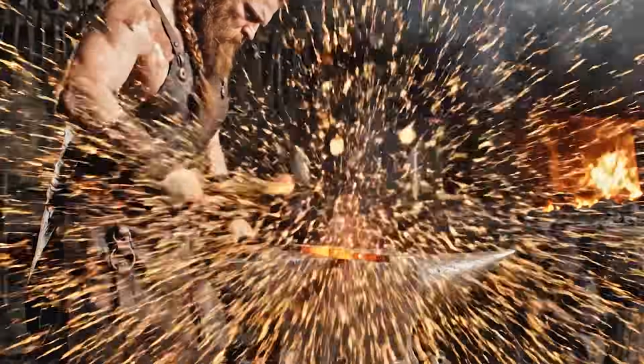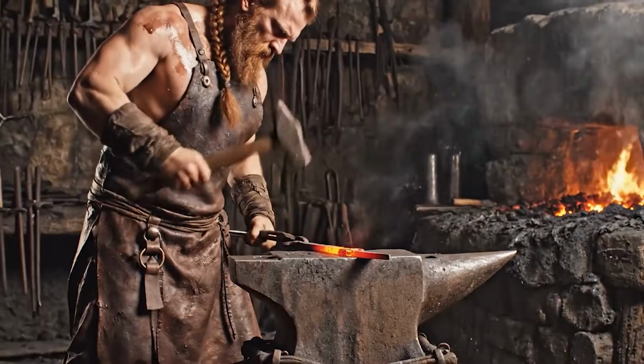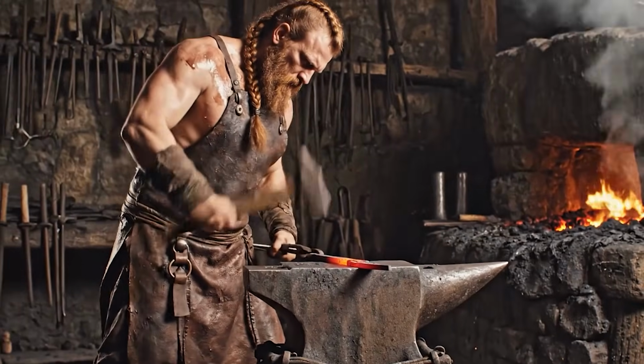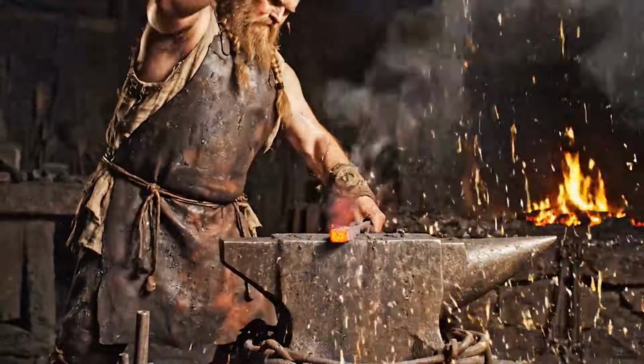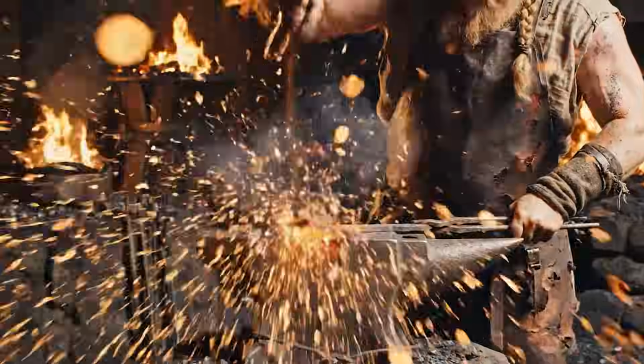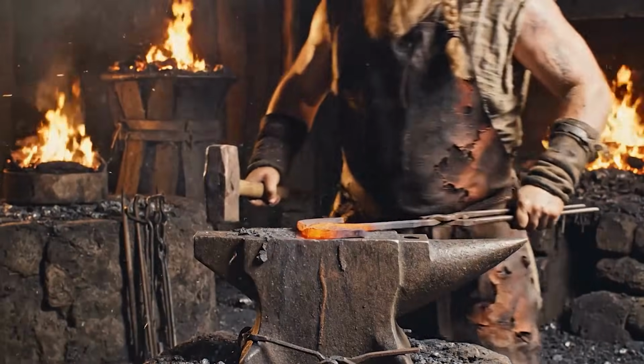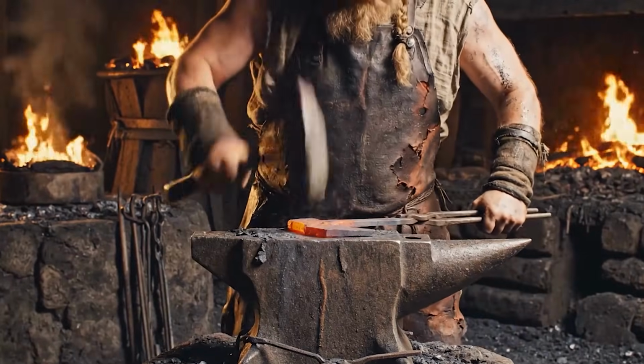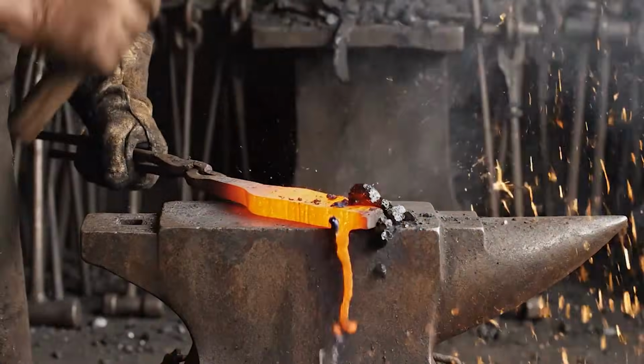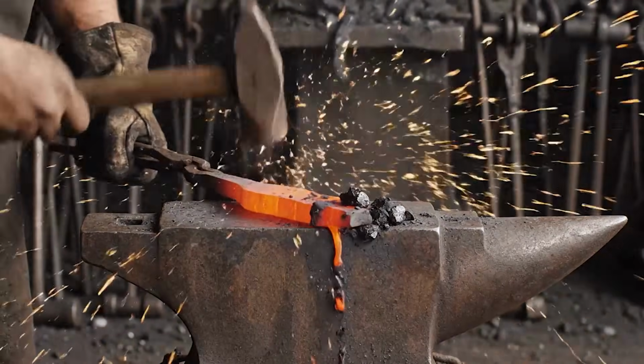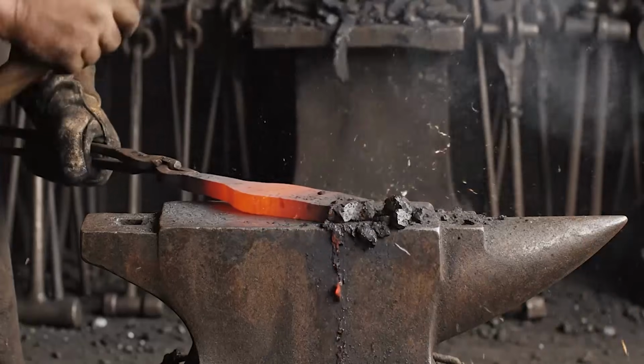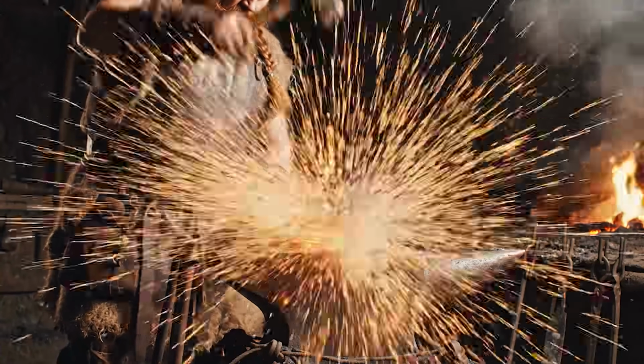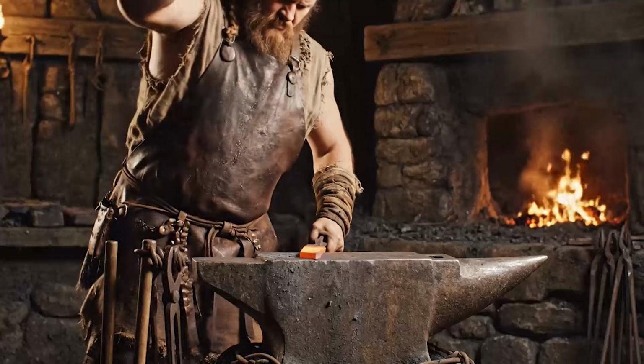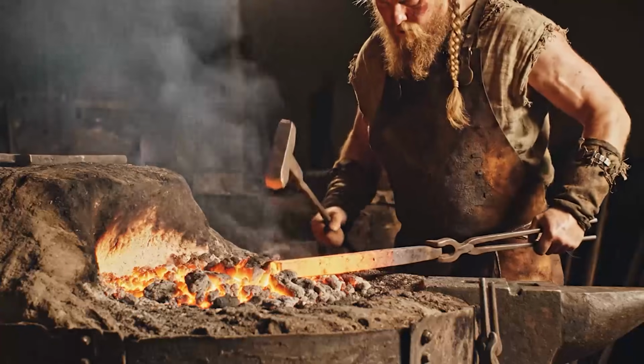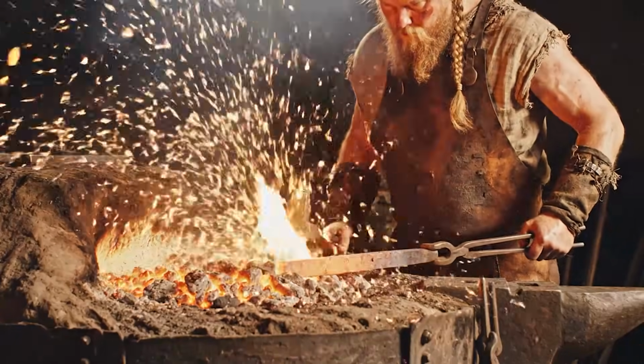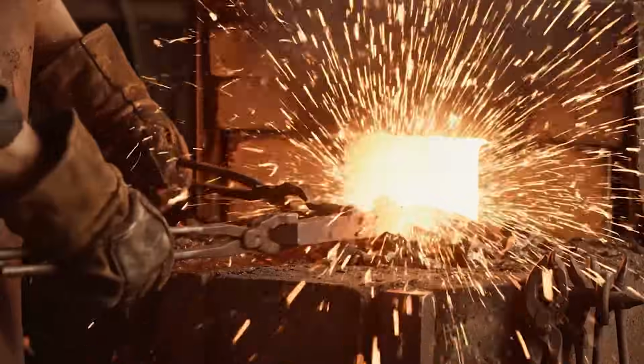This process was repeated over and over again. Forging, folding, welding. Each cycle served several purposes. First, with each folding and forging, another portion of harmful slag was squeezed out of the metal. The slag flowed out in the form of liquid sparks, and the metal became cleaner. Second, the inner layers of metal were mixed together like dough, making it more homogeneous. Most importantly, each time the metal was heated in the charcoal furnace, it absorbed carbon.